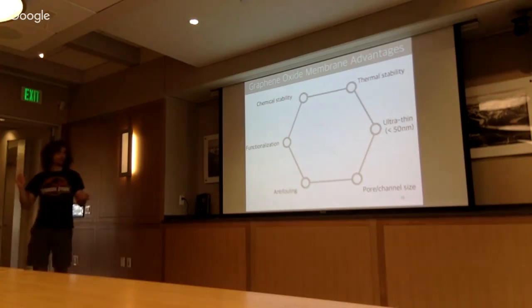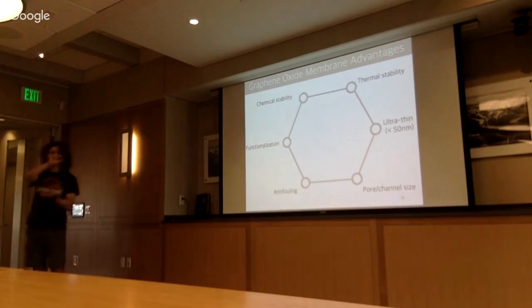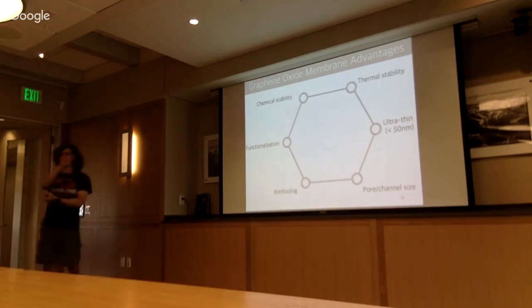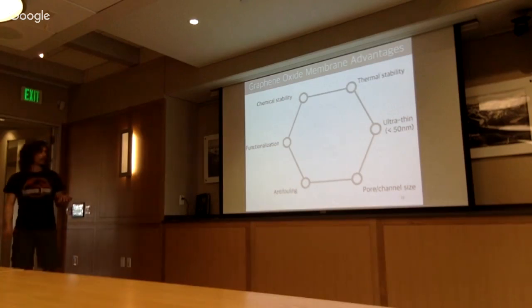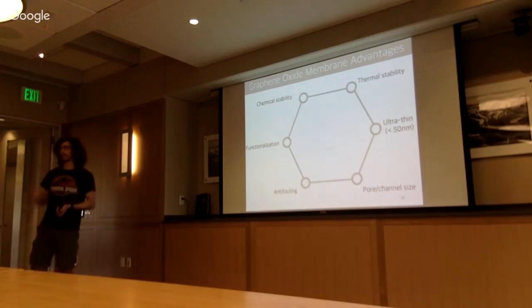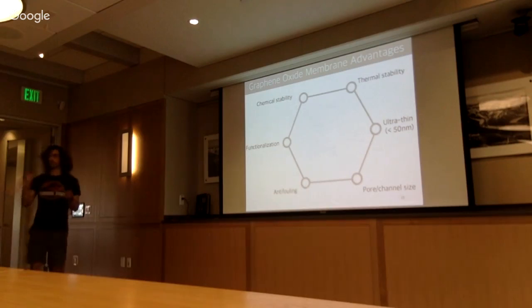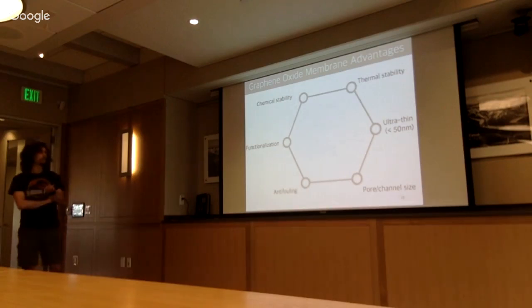And you can tune the pore size, and it's intrinsically anti-fouling. So you remember this carbon layer, this organic layer that creates on the surface? In graphene oxide this tends not to form. And finally, you can functionalize, which is just a fancy word that means you can attach molecules to it.